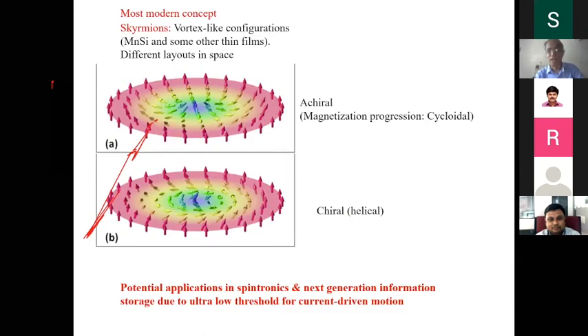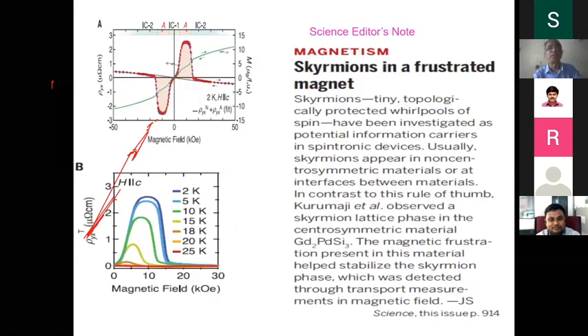And I just want to tell you there's a paper recently in Science, the material which I found just now, the another phenomenon called skyrmions was found out by a Japanese group, and there are certain experimental features like typical Hall effect. You see, these are typical Hall effect features. Only experts can understand better. We plot Hall data as a function of magnetic field. There's a maximum here. The same data we published 2 decades ago. These are typical signature of skyrmion behavior.